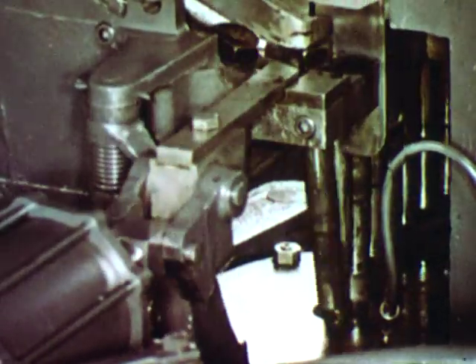Before the 1¼ bolt maker, cap screws of this size were produced on hot upsetting machines, usually by hand. By cold forming in the bolt makers, no further machining is required. The fatigue life of large cap screws, cold forged with rolled threads, is twice that of parts made by other methods. Tensile strength is 12.5% greater.